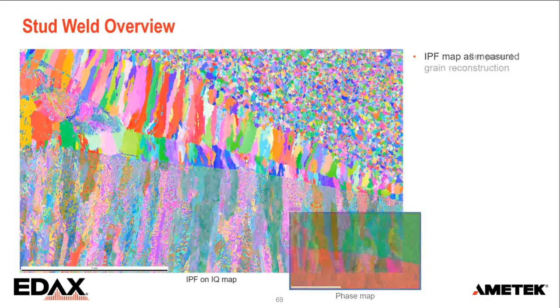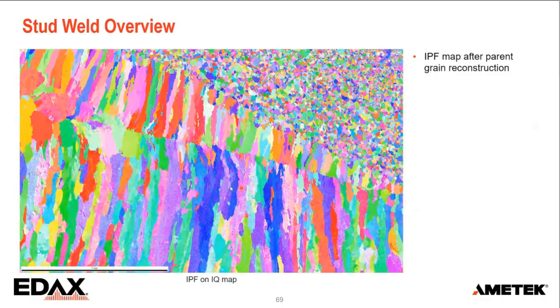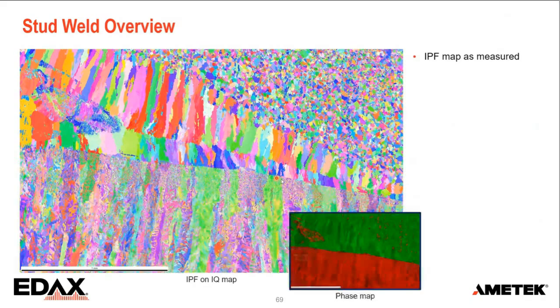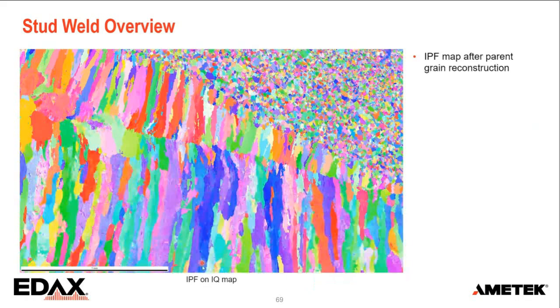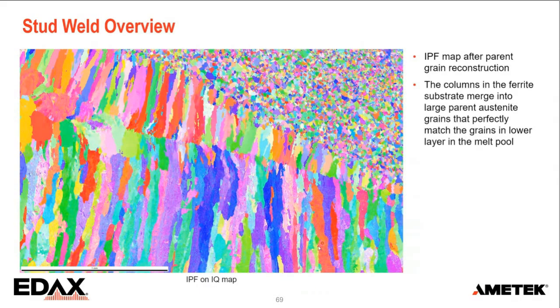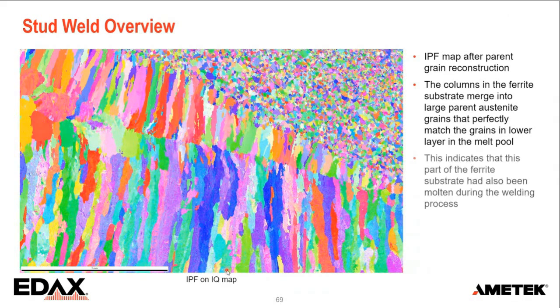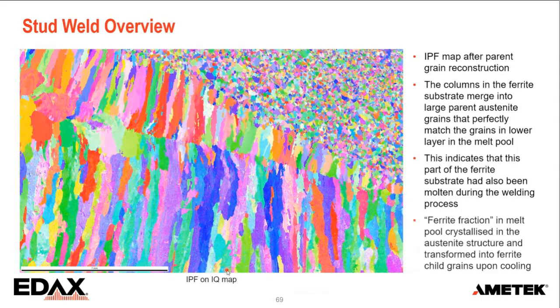And now you can see that the entire ferrite structure here at the bottom is perfectly continuous into this lower band in the former melt pool. And that means that this was part of the melt structure and that it actually crystallized in the austenitic structure and only later transformed back to ferrite.